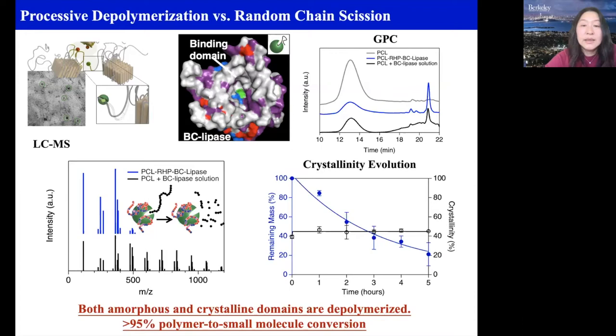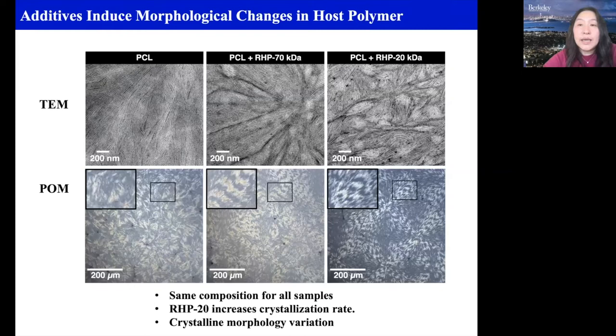That all seemed good till one day we realized that the polymer matrix morphology is very sensitive to the addition of additives. And additives are not avoidable when you start to think about plastic manufacturing. There's not even a single product out there made of one type of polymer. There are always additives, there's always other components. And the addition of a blend or additives will change how the polymer crystallizes. In this case, we purposely introduced the additives. We want to change the morphology of the host matrix to see how that is going to affect the degradation, as well as the extent of degradation.